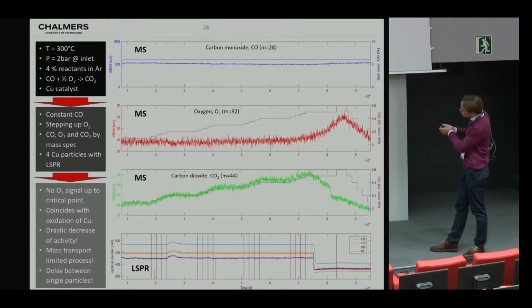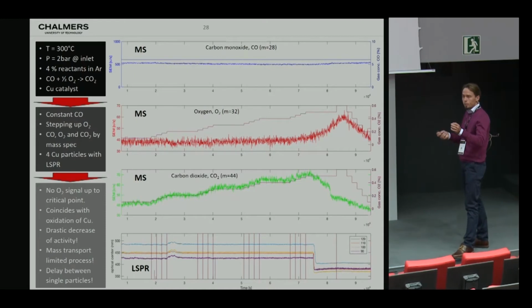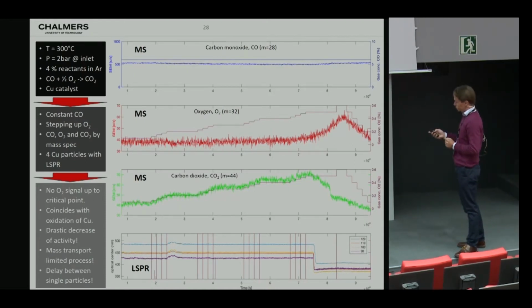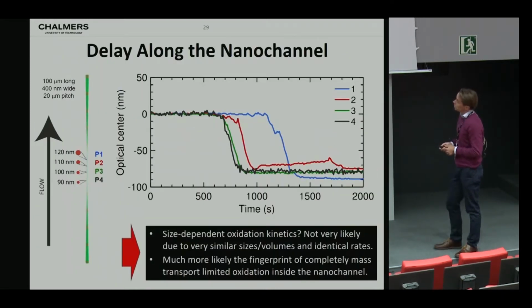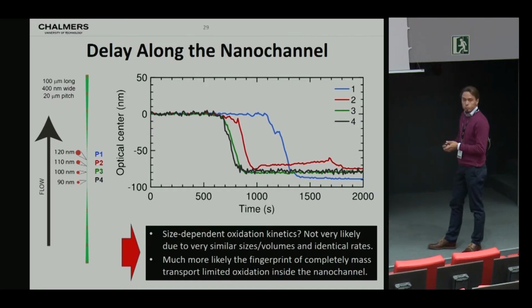And most interestingly, if we have a close look here, we will see that there is a time delay in the switching from the metallic state to the oxidized state for these particles. And this becomes very clear in this picture as we zoom in, where you can see that the time delay is substantial. And you can ask yourself, why is that so? Is it the size dependence of the oxidation kinetics of copper? As I said, I don't think so, because these particles have almost the same size, and in fact, the transition occurs at the same time scale.